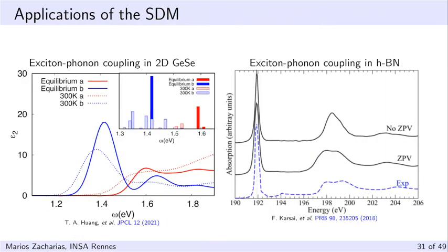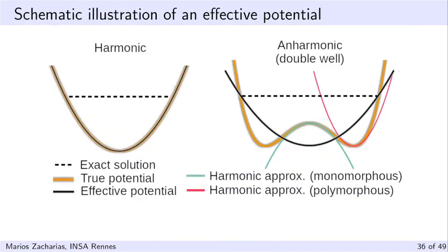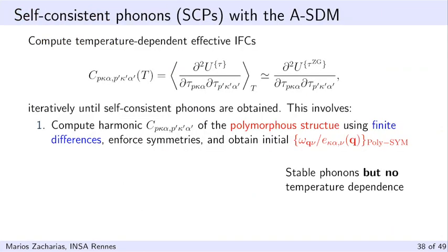Oh yeah. So basically, the point here is that when you have the harmonic approximation and well-defined phonons, you can just use a single configuration generated by these phonons with the equation I have described for the special displacement method. But when we have anharmonicity in the system, inevitably we need to use a few more configurations. In principle, it can be 2 configurations or 3 configurations, as I demonstrate here.